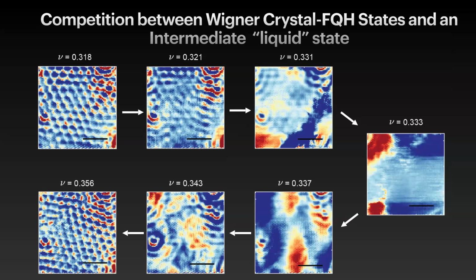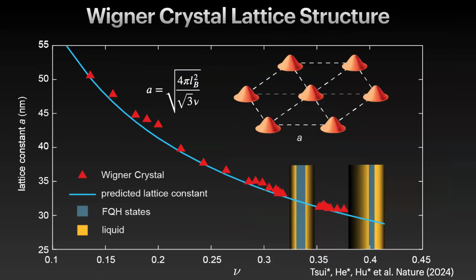Let's first focus on the simplest thing, which is just the lattice constant. So remember, the only thing that this lattice constant depends on is just the charge of the electron. And there are no adjustable parameters. So that's the blue line, okay? And we know the magnetic field, and then you do the filling, and this is your lattice constant. And I've only put on this picture the places where we have both translational and rotational symmetry breaking. There are places in between where the rotational degrees of freedom seem to be melting because of disorder. It's pinning itself to whatever disorder you have in the sample, even how little it is, it's still pinning. And it melts away as you go towards these incompressible states.